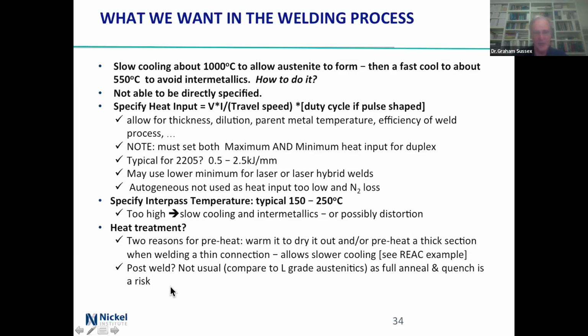And afterwards, it's not usually, I mean, it's much the same as looking at L-grade austenitics, because post-weld heat treatment for getting rid of carbides, you don't have an issue with it. A full anneal and quench is just a bit of a risk.